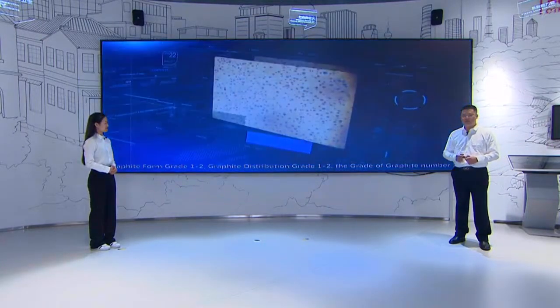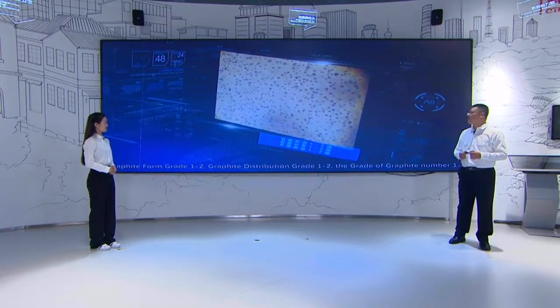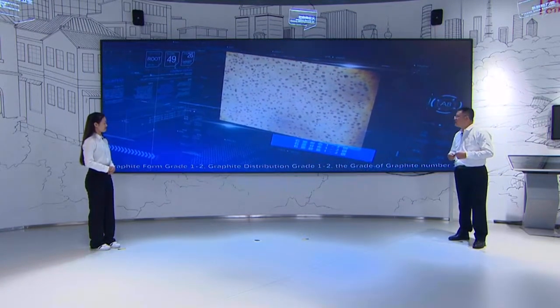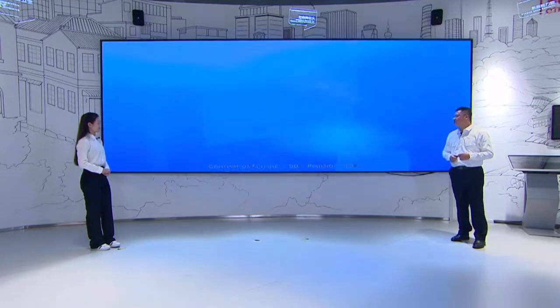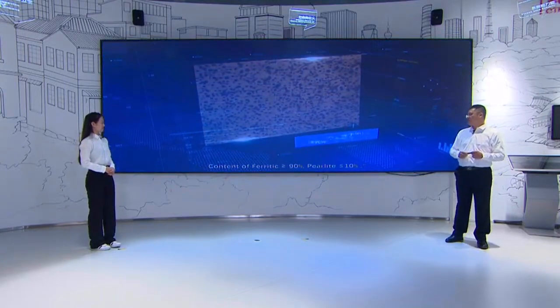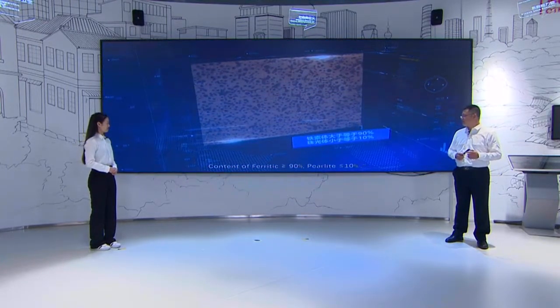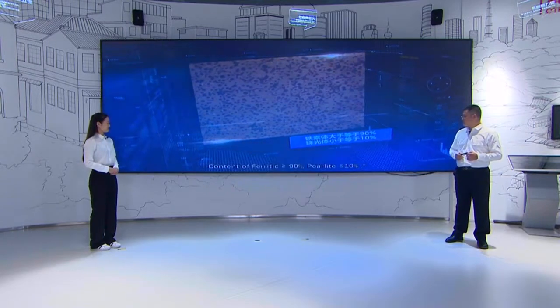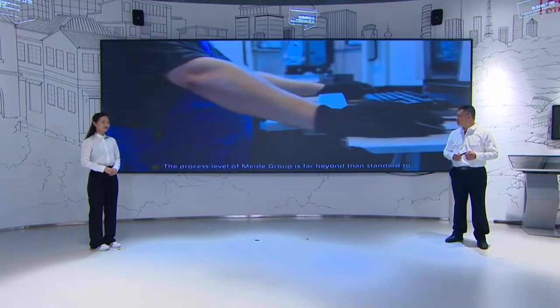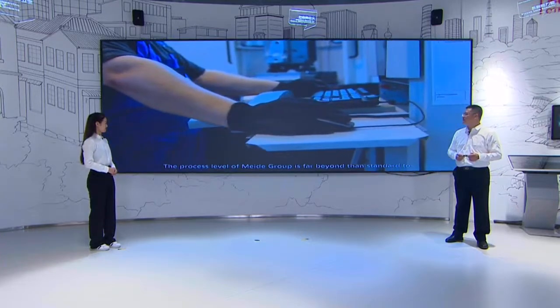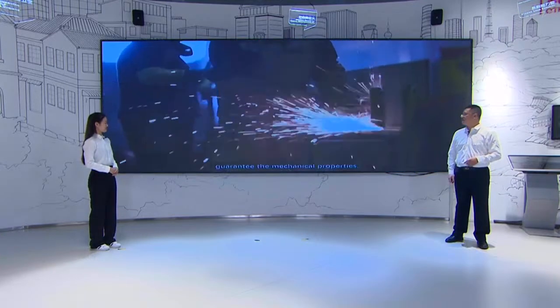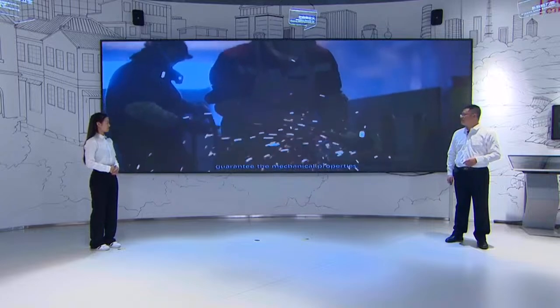Graphite form grade 1 to 2. Graphite distribution grade 1 to 2. The grade of graphite number 1 to 2. Content of ferrite greater than or equal to 90%. Pearlite less than or equal to 10%. The process level of Meide Group is far beyond the standard to guarantee the mechanical properties.